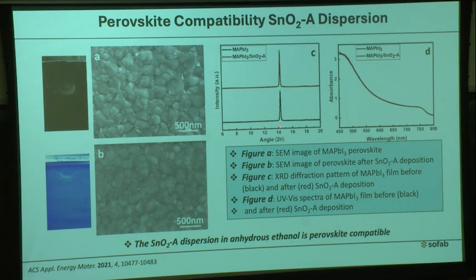This peak, presented at 14.2, is the signature peak of the perovskite. After tin oxide deposition, there is no change in perovskite position, and those peaks are exactly aligned with each other. So even after tin oxide deposition, the perovskite is still in the perovskite phase. Also, whenever perovskite undergoes degradation, it makes lead iodide.